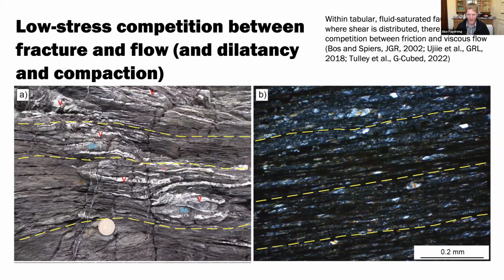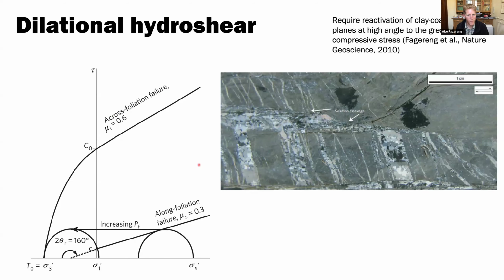But if you can't quite, then you might have layers where you are accumulating elastic strain locally, and sometimes have to have earthquakes to catch up, as well as the heterogeneity internally. So we looked at this concept quite a long time ago now, and named it dilational hydroshear. The idea was that if you're going to have more space across foliation failure, that requires Byerlee friction, that requires stresses we probably don't have, because pressure solution occurs at much lower differential stress than that.